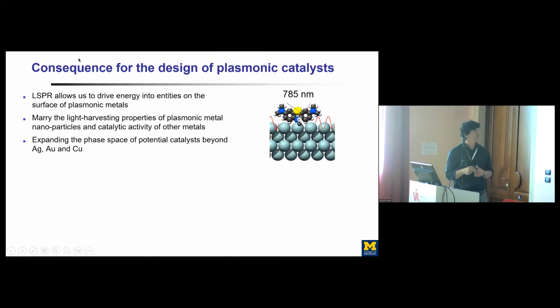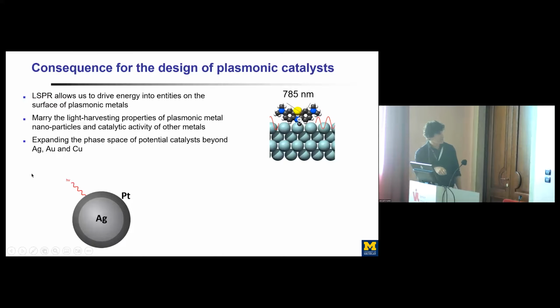So how this mechanism plays a role might not seem that important. I mean, the electron ends up in this molecule or this entity that's attached to the nanoparticle, so who cares how it takes place? But it actually has a nice consequence, because it allows us to build a framework for expanding this plasmonic catalysis beyond silver and gold. So what this is telling us is, if I have a silver nanoparticle, I can get localized surface plasmon resonance to collect energy that's interacting with light. And if I now put something that has a larger imaginary dielectric function than silver around this, that energy is preferentially going to be dissipated through that entity.